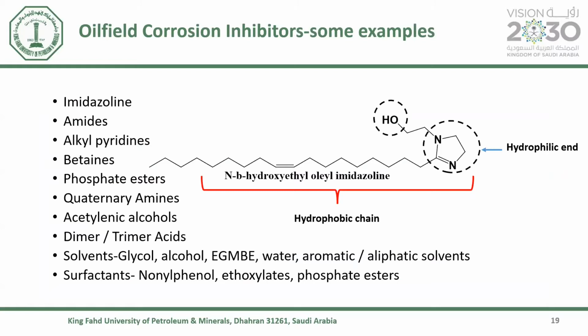So here we have some typical examples just so that you can really see some examples of corrosion inhibitors. And in this diagram, you see how it works. So you have the hydrophilic end. This end can bind to the metal surface. And then you have the long alkyl chain ends. So this end will form the hydrophobic film on the metal surface and then displace the water from the surface. So these are some of the typical examples. Like typically in the industry, they use imidazolines, amides, alkyl pyridines, phosphate esters, quaternary compounds. And then they also use some solvents and surfactants.